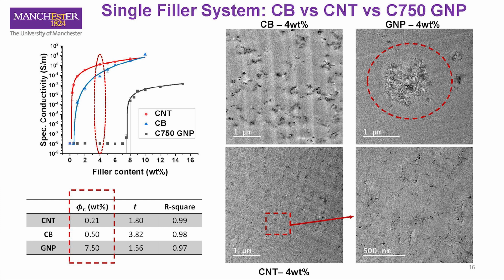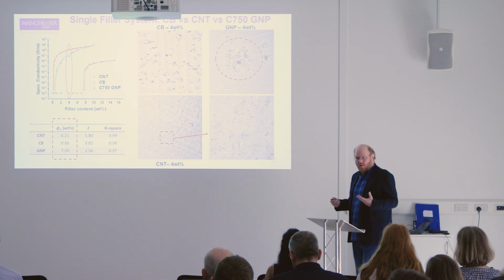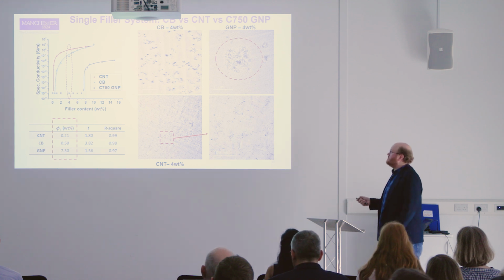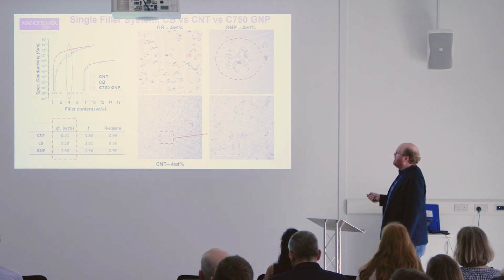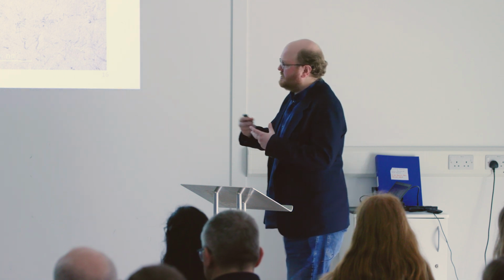As you can see, the nanotubes and the carbon black percolate at a very low filler loading, less than about 1%. They become conductive very quickly. This particular graphene doesn't become conductive until 8% or so, or even more. To understand why, you do an extra analysis of the morphology. If you look at the TEM images here, you can see this carbon black is reasonably well dispersed. You've got particles everywhere. You can obviously see that as you increase the loading, you're going to get some kind of continuous pathway.